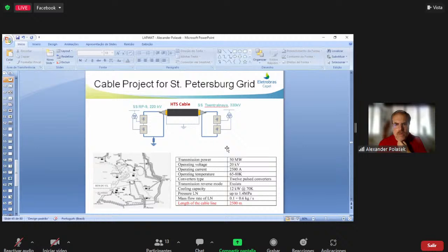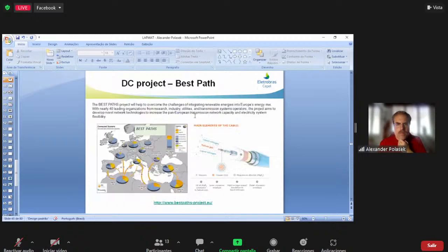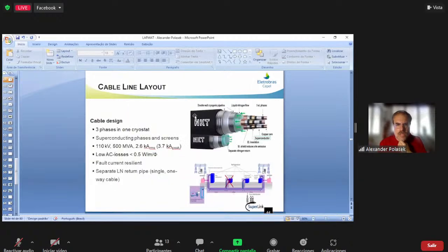It's another ambitious project in St. Petersburg in Russia to achieve 2,500 meters with high temperature superconducting cable connecting two substations. These cables are AC cables, and they have AC losses, as I told you. In this case, the AC loss is less than 0.5 watts per meter. That's a very nice value, because normally AC losses can be higher than this.